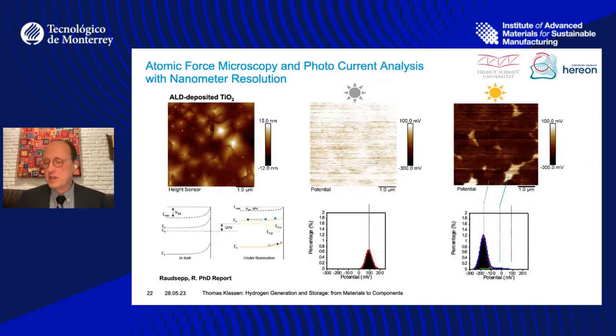So this is more intuitive and easier to understand. Atomic force microscopy and photocurrent analysis with nanometer resolution. So we can have a look at the deposited titanium dioxide or any other photoactive material. And we basically get here a height profile in AFM.